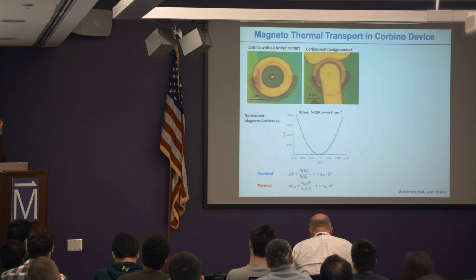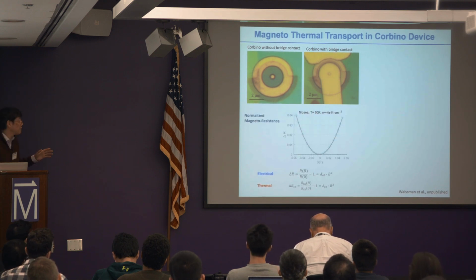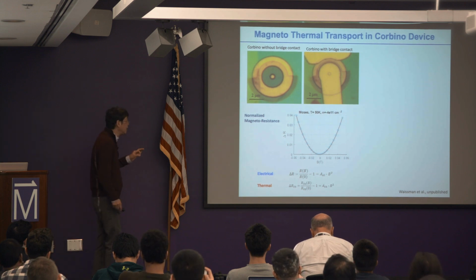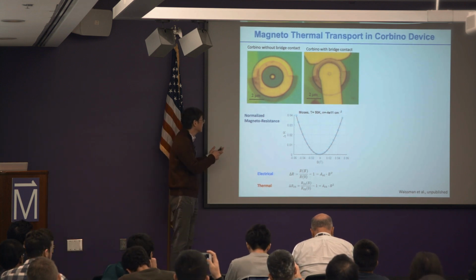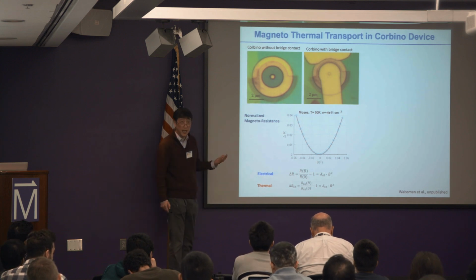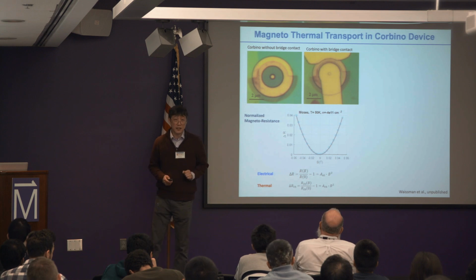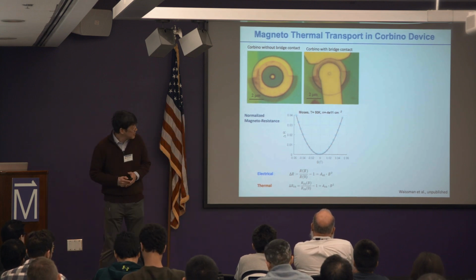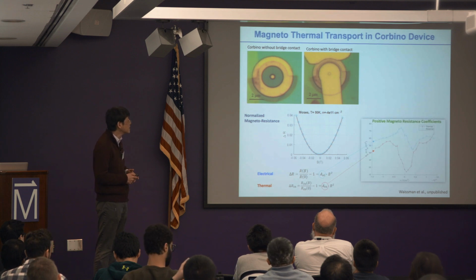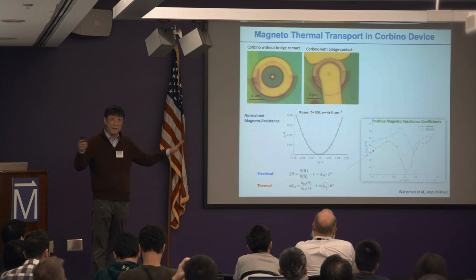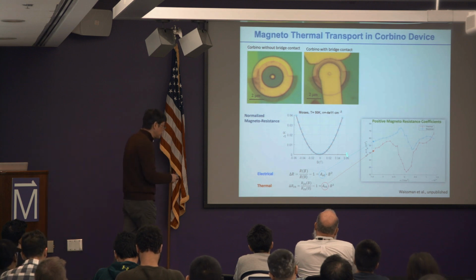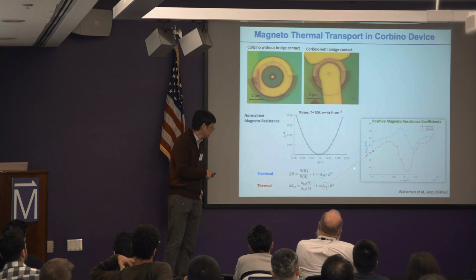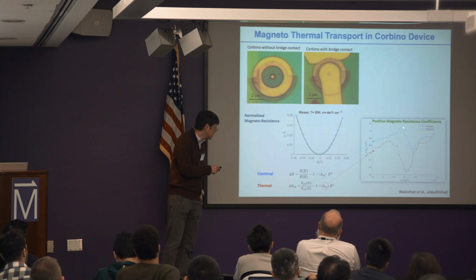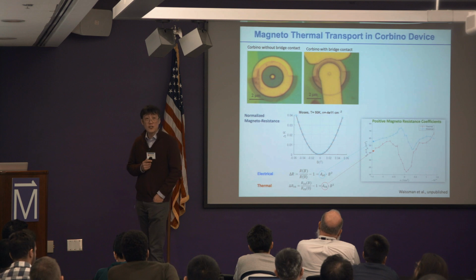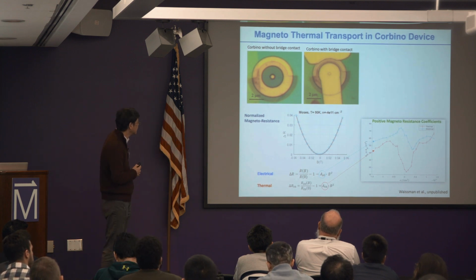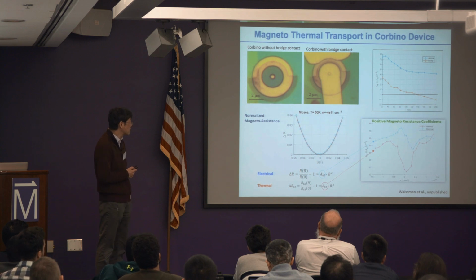So this is an ongoing project, so I don't have much to say. But what you are seeing here is if you measure electrical conductivity, electrical resistance, and the thermal resistance or conductance across these Corbino devices under the magnetic field, we start to see positive magnetoresistance, both in the electronic and thermal sectors. It seems like they have some relation outside of this heavily doped regime. So again, in the Fermi liquid regime, it seems like we restore back to the Wiedemann-Franz law, even with the magnetoresistance. But near the Dirac point, there is a strong deviation, especially a strong suppression of this magnetothermal resistance near the Dirac point, and it even changes sign at higher temperature.